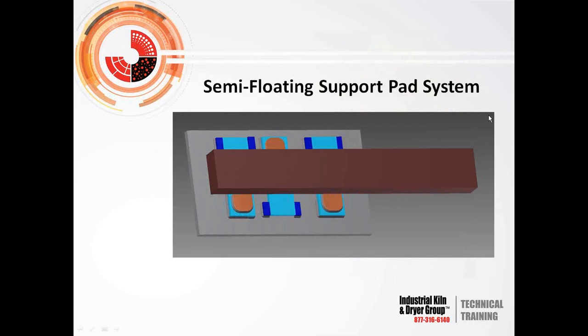One thing that happens on tire pads, and just a good example of it: if you have a high-speed application like a dryer or some of the new cement kilns that run like 3 RPM, although I've seen floating tire pads that work at 3 RPM on an 18-foot kiln, if they flop too much or clunk, they will move. They'll be loose at the top and then tight at the bottom. Sometimes it's a good idea to just weld one end of the pad and leave the other end free for shimming. This is what we call a semi-floating pad system.